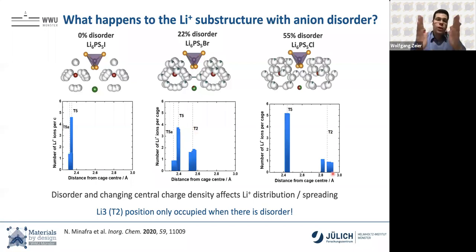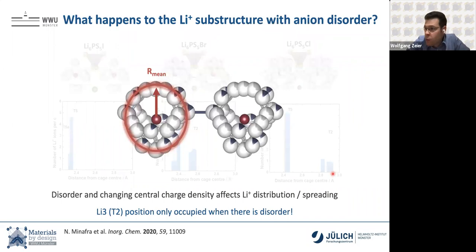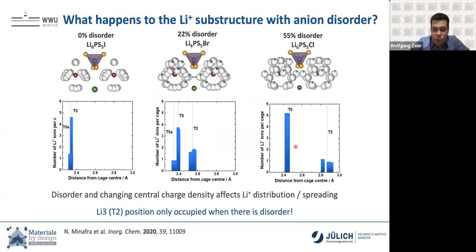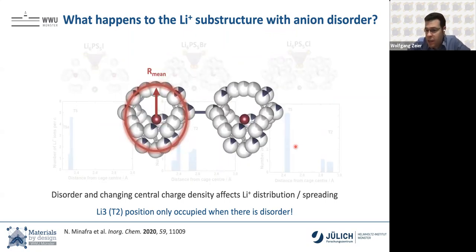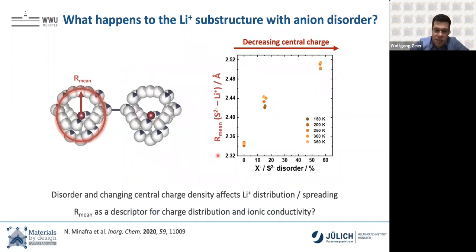And this is weird, right? The iodide is a large unit cell. The bromide is a smaller unit cell. The chloride is the smallest unit cell. But even though we have the smallest unit cell, the distances in the unit cell are larger. Why is that? Well, instead of looking at these radial distributions, we're now going to define a mean radius, the average radius weighted by occupancies away from the center of this cage. And if we plot this mean radius as a function of the disorder, the mean radius increases as a function of disorder.